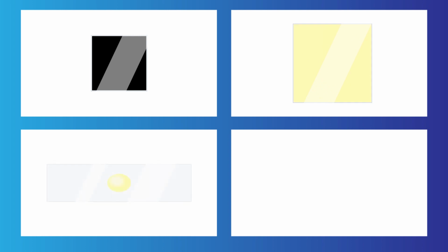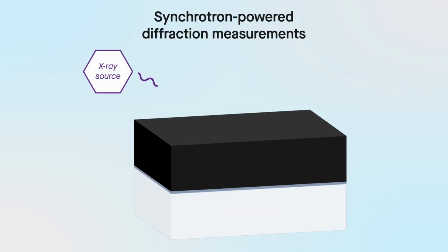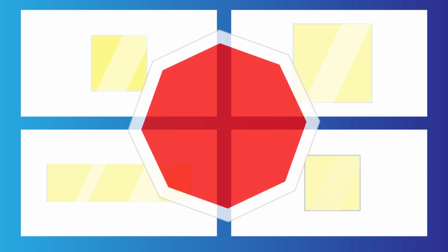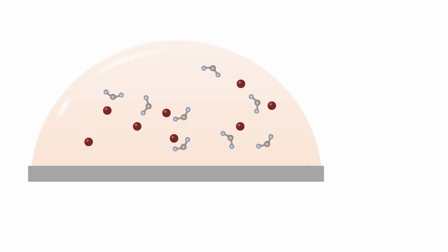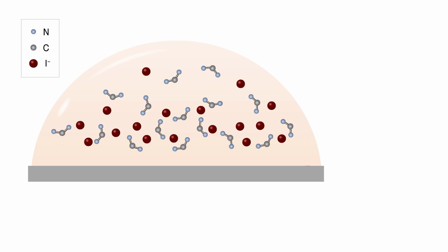It's a problem that's long plagued materials scientists, largely because the perovskite grows much faster than they can track it. Now, using synchrotron-powered diffraction measurements, researchers have watched the process unfold. Their findings not only explain how the pesky yellow phase arises in perovskite films, but they also point to ways of stopping it. Using a specially designed spin coater attached to a synchrotron beamline, the team monitored the chemical species that formed when combining the ingredients for producing films of formamidinium lead iodide.